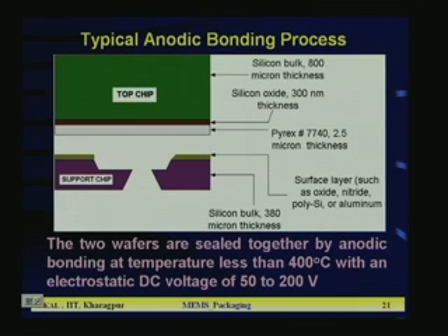Now, here a typical anodic bonding process is shown. For example, here is a silicon chip with silicon dioxide of 300 nanometer thickness, and this is Pyrex 7740 glass, 2.5 micron thickness. Top wafer is 800 micron thickness. The bottom silicon wafer is 380 micron. There you can see the surface layer, such as oxide or nitride or polysilicon or aluminum, whatever it is, and the support chip is there. They are going to bond together using the anodic bonding technique.